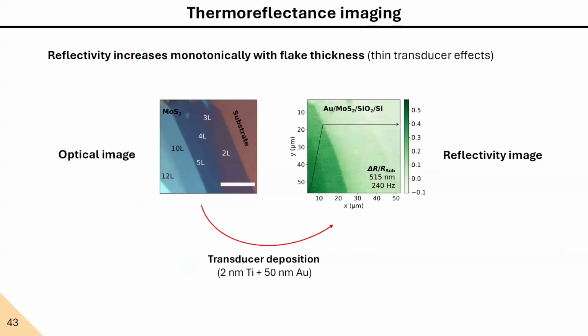To understand this, we performed several imaging techniques. First of all, our optical images of the flake before we deposited our transducer material show a nice optical contrast for the different layers. But once we deposit our metal transducer, now we're covering them with metal, we cannot distinguish the different layers of the flakes, but we do see an increase in reflectivity of our probe beam as we increase the thickness of the material. And this is because we're using a quite thin transducer layer.